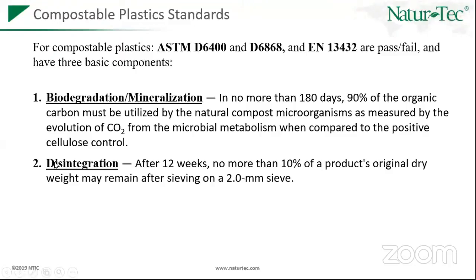But the reason they also put in disintegration is to check whether the material gets assimilated into a form which is indistinguishable, or does it keep lying out in patches? This is what the disintegration test does. If you have, let us say, a metallized structure, like a metallized film or an aluminum foil laminated with a compostable film, does the product get disintegrated after sieving on a 2 millimeter sieve? You should not have more than 10%. So this is the second component in the standard.